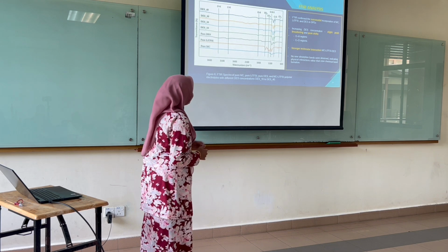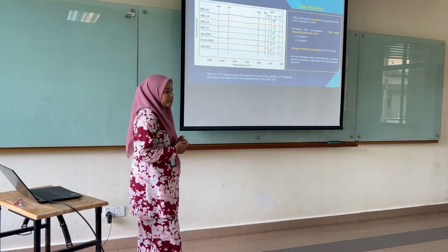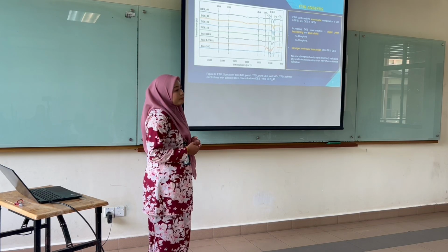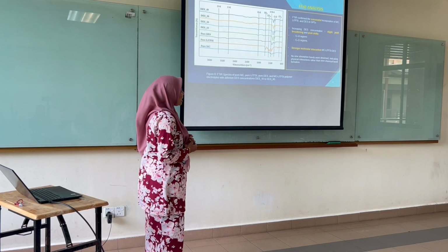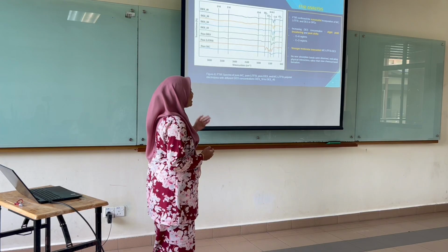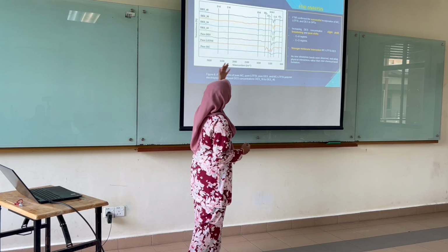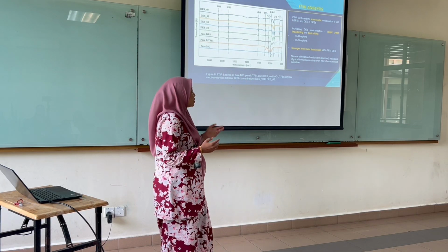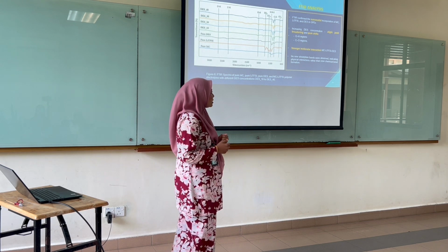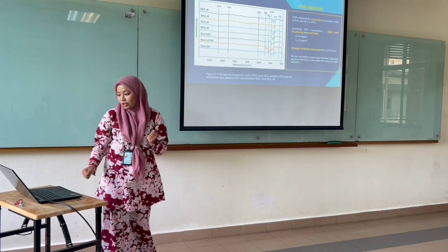This is the figure of FTIR spectra for pure MC, pure LiTFSI, and pure DS with different DS concentrations. The FTIR spectra confirm the successful incorporation of MC, LiTFSI, and DS in the gel polymer electrolyte. With increasing DS concentration, slight peak broadening and peak shifting are observed at the OH region and CO region. This is because of stronger molecular interaction of MC, LiTFSI and DS. As you can see, no new absorption band was observed, indicating physical interaction rather than new chemical bonding was formed.